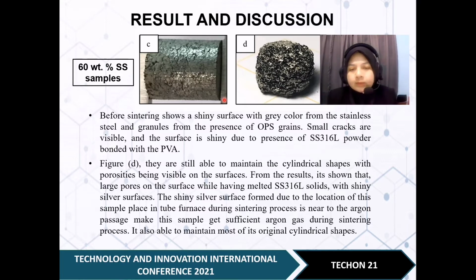After the sintering process, as we can see in figure D, the sample still maintains the cylindrical shape with porosities formed on the surface of the sample. We can see the porosity here. From the result, it is shown that there is a large pore on the surface while the stainless steel has melted solid. So the sample is still solid, melted solid, but having porosity in its body, with a shiny silver surface.